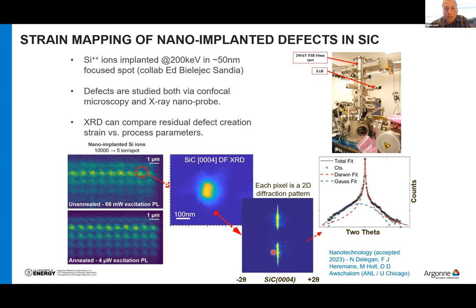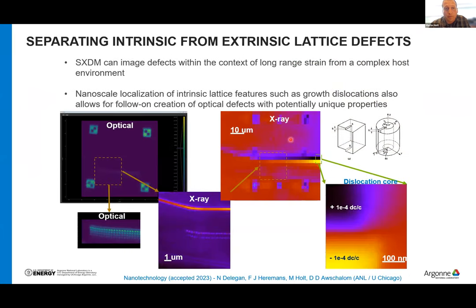Here's a viewpoint of what the detector is seeing per pixel. And most of this doesn't know about the defect cloud. And there's a small little wing of expansive strain near the defect that you can actually resolve and pull out the local strain as you walk across it. But it's not just an in situ strain map, which is important especially for annealing steps and figuring out how to control that. We can also see things that are optically quiet that you wouldn't be able to resolve through optical methods.